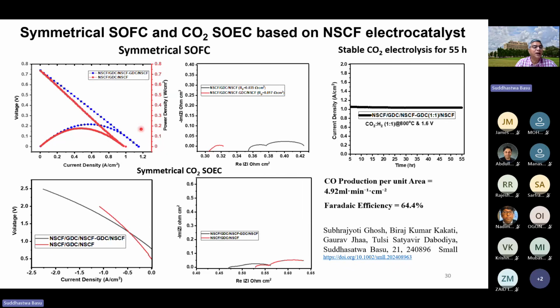So that is how we got this blue color and a slightly larger power density, which is about 0.2 watt per centimeter square. A reasonably good current density, as we are showing you here, and lower voltage. When we have less polarization resistance with the functional layer, the red one, compared to no functional layer like the GDC NSCF functional layer we added, very good current density was maintained up to about 55 hours. And this is symmetric SOFC, and this is symmetric CO2 SOEC.